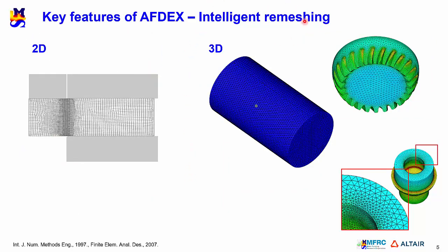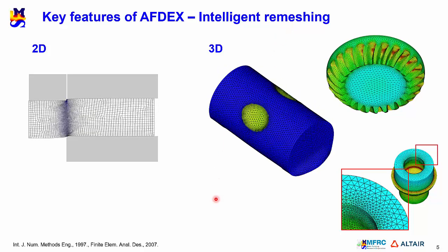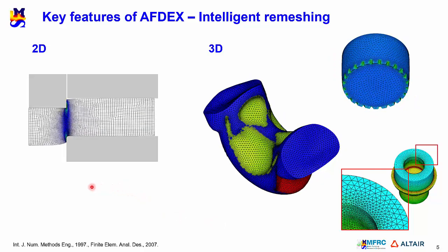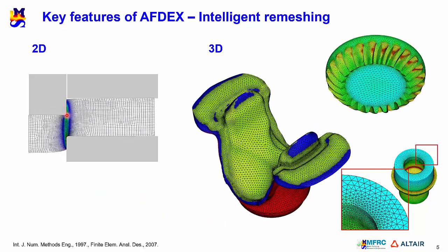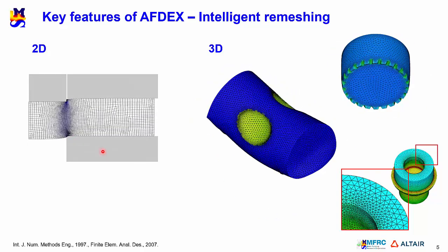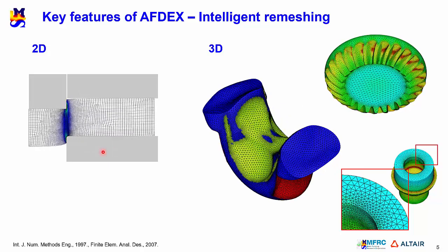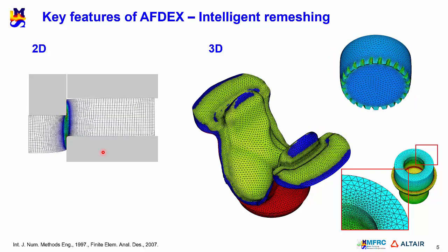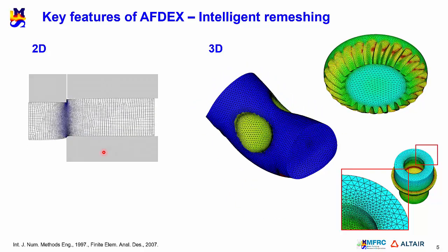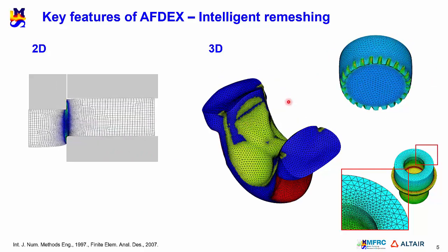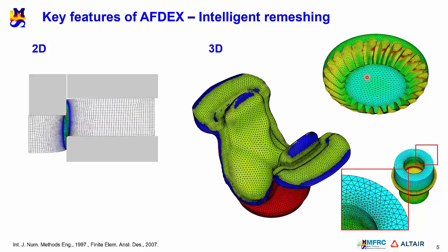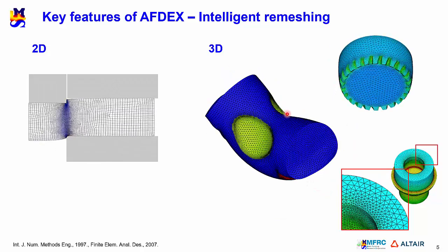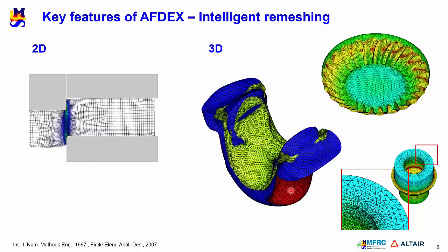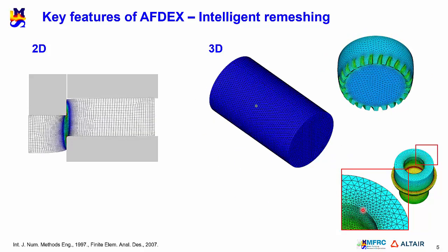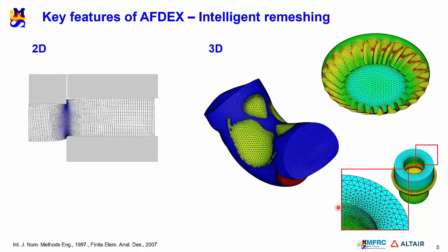Remeshing is of great importance. In structural engineering, the more advanced the FE mesh system, the better the result. It's true, of course. To the contrary, in bulk metal forming, small finite elements may cause too frequent remeshing, especially around sharp concave corners. So an appropriate element size for metal forming process exists, which trades off the interpolation error and remeshing error. When the mesh system describes the material with acceptable accuracy, it can be a good engineering solution. You can see that all mesh systems here describe the material with good geometric accuracy in terms of the tolerance. For example, these chamfered corners were well described with a limited number of finite elements.